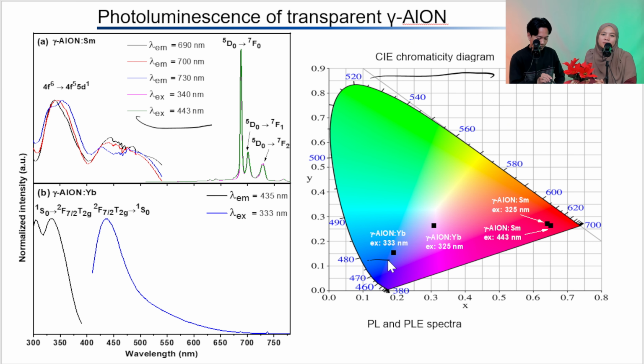Like you see here, this is excitation at 333 nanometer. It shows a kind of blue color, but when you slightly shift the excitation to 325 nanometer, then it will show almost a white color region. But with samarium, it basically just shows red color. So up to now, mostly they can generate what kind of color? For this transparent gamma AlON, so far I've just observed bluish white or just blue with ytterbium, and red color with samarium. And with other rare earths, it basically doesn't show any absorbance or photoluminescence properties.